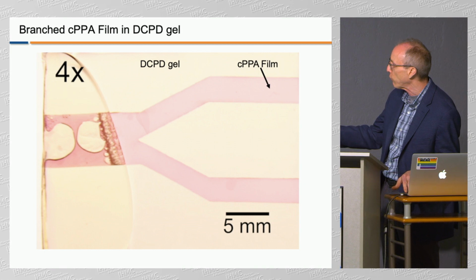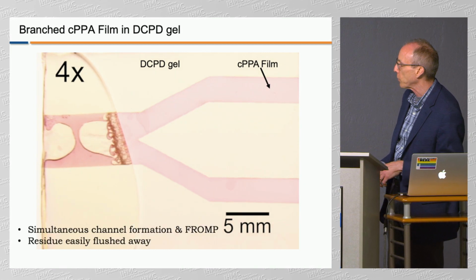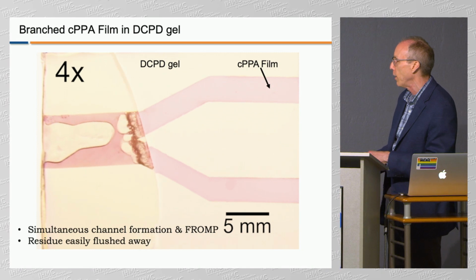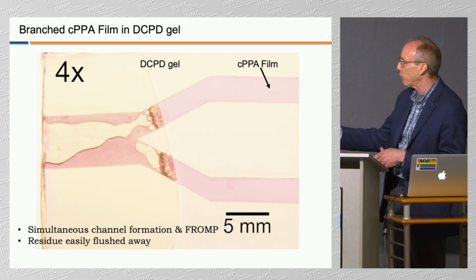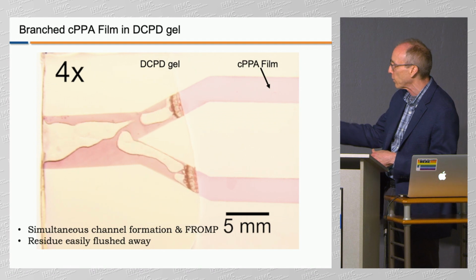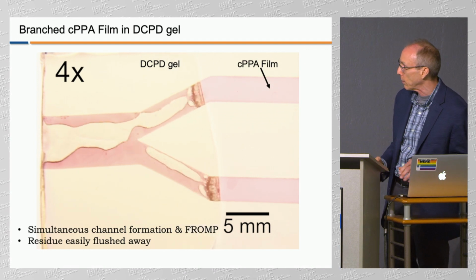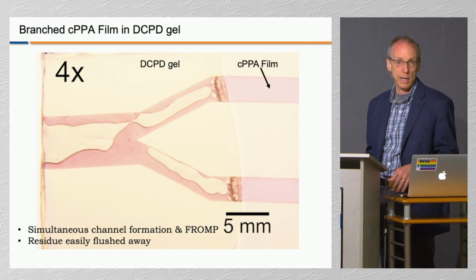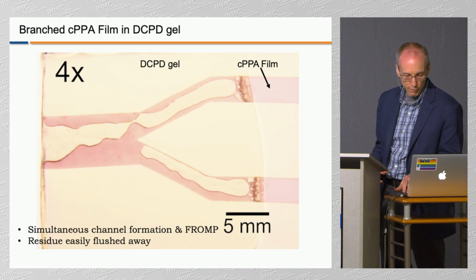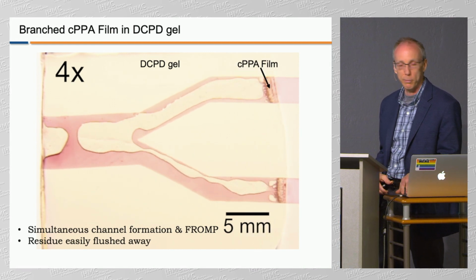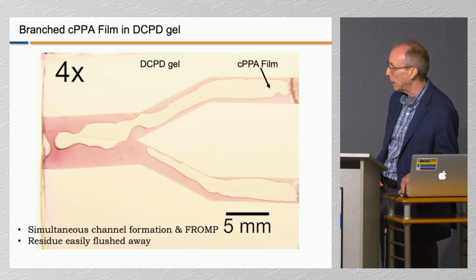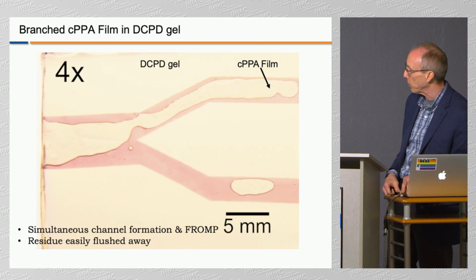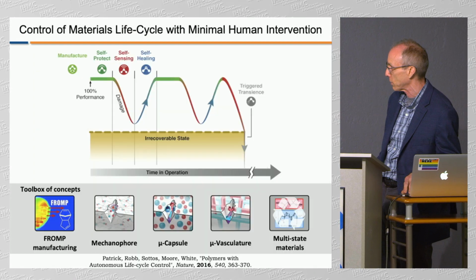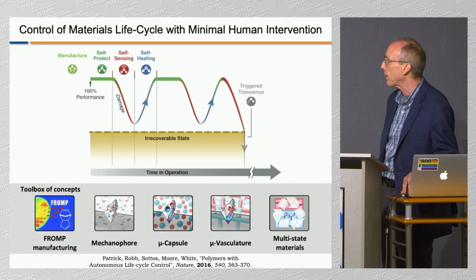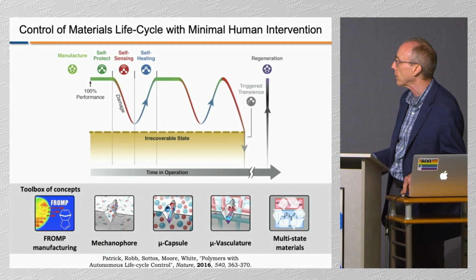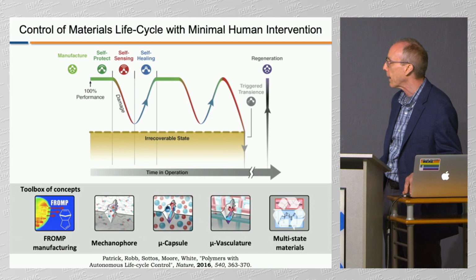Like, this is a thin film. It shows a branching effect. So the depolymerization follows the branch, and the front is there, and it's really turning out to be quite a robust technology to simultaneously vascularize composites while they're being manufactured, using the heat of that frontal ring opening metathesis polymerization process.